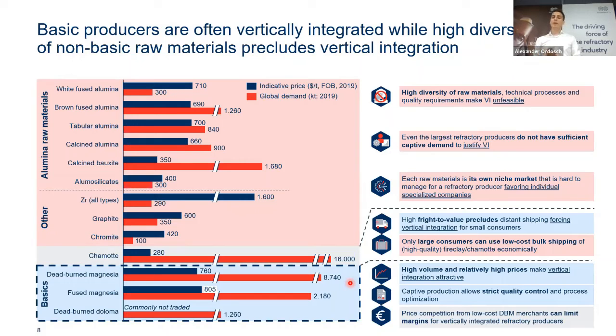And this now immediately tells you that the low-hanging fruit in terms of vertical integration is the raw materials that you need in high quantity and that have a comparably high price. If you compare, for example, the dead burnt magnesia price of, let's say, 760 with the non-basic raw materials, you see that the 760 is actually quite in the high range of the whole price series. For fused magnesia, it's even more, with more than $800 a ton common prices. And therefore, vertical integration is actually only attractive to refractory producers in the basic area.